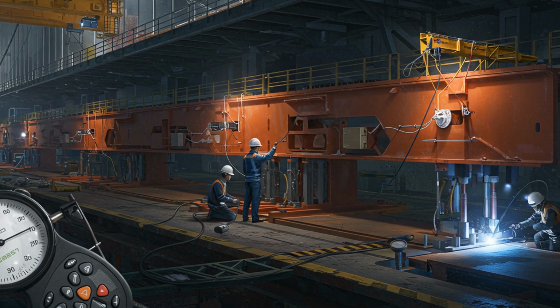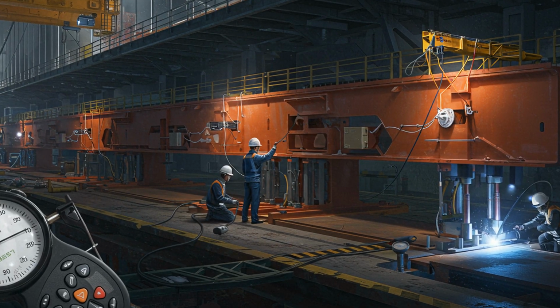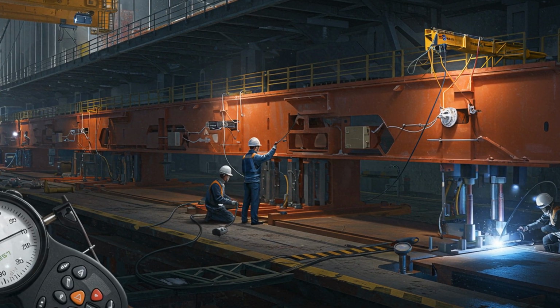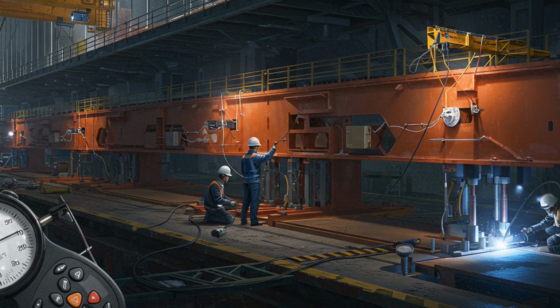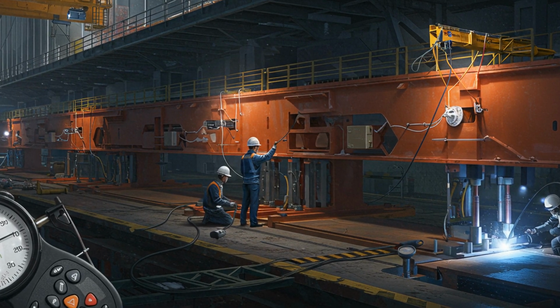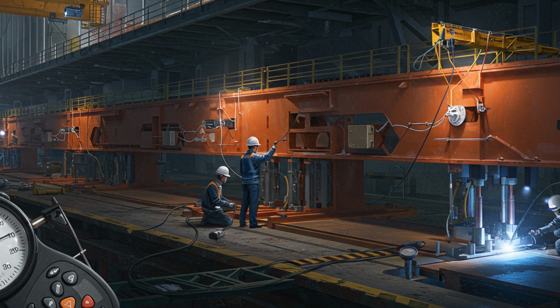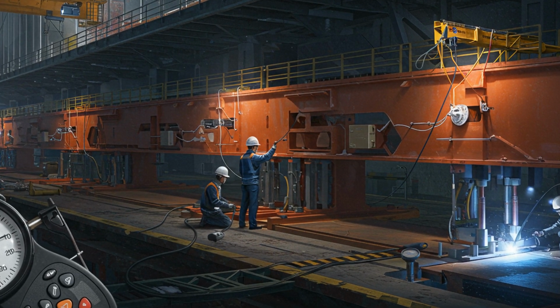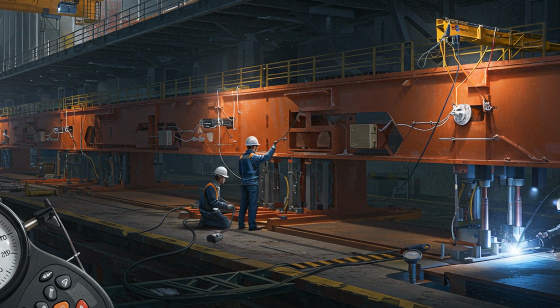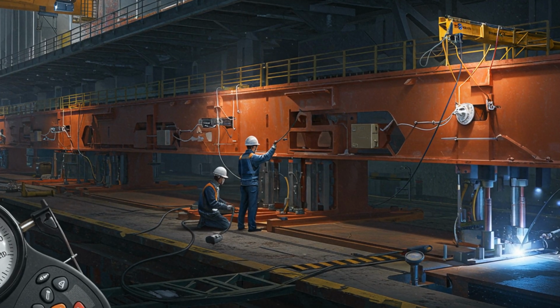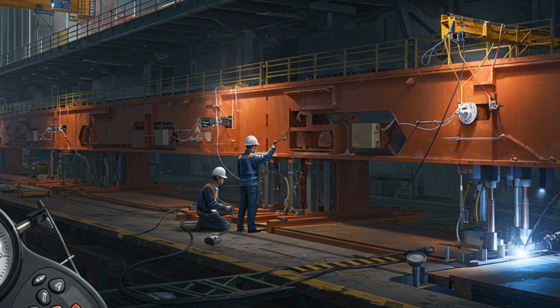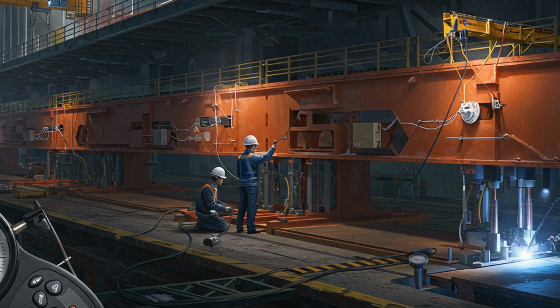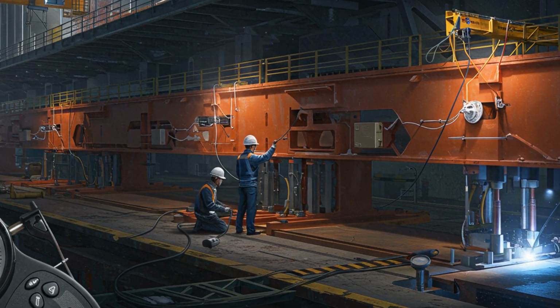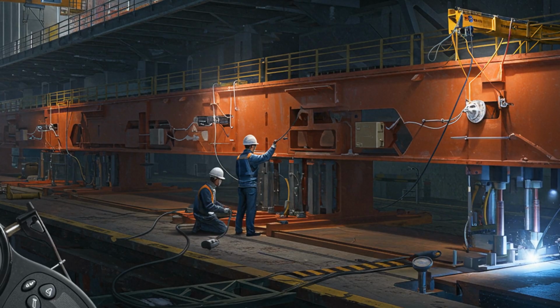Hydraulic jacks or calibrated weights apply loads to the deck while engineers measure deflections and strains using strain gauges, load cells, and displacement transducers. Cable inspection uses acoustic emission monitoring and electromagnetic methods to detect broken wires in a main cable without dismantling it. Corrosion protection systems receive adhesion and thickness tests, coating thickness measured in micrometers, and holiday detection used to find defects. Fatigue checks use historical traffic spectra to project remaining life.